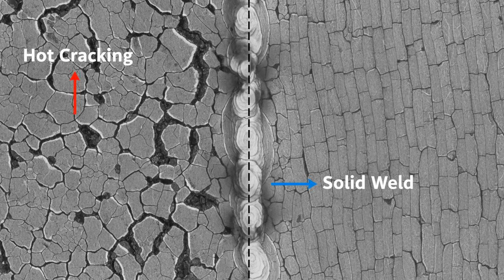To understand why this is such a big deal, we have to understand the problem with traditional superalloys, like Inconel 738 or MAR-M 247. These materials were never designed to be welded. When you subject them to the intense, localized heat of a laser in laser powder bed fusion, they suffer from something called hot cracking, or strain age cracking. As the metal solidifies rapidly, it leaves behind microscopic fissures. In a flight-critical part, that is a catastrophe waiting to happen. For years, the industry compromised by using lower-performance alloys that were weldable, like Inconel 718. But that compromise is effectively dead.